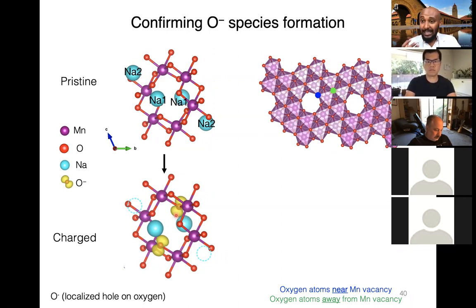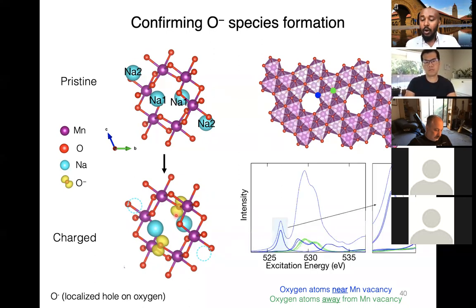Based on this understanding, if you perform a simulation of the XAS of this material, you see that this pre-edge feature we are observing in the charged system in the experiment is actually coming from two oxygen atoms where we have the O- species. So in other words, the O- species are giving us this pre-edge feature that we uniquely observe in this material that's correlated also with the low hysteresis. So we indeed form O- species in the material, and this might explain why we also have the low hysteresis in the system.